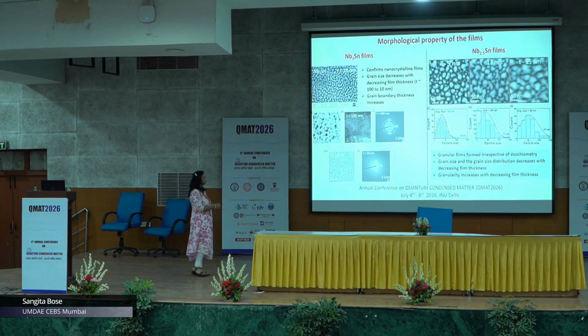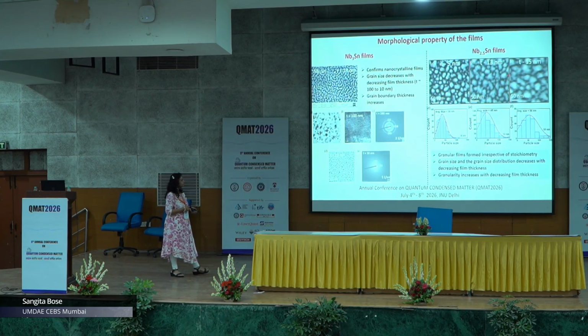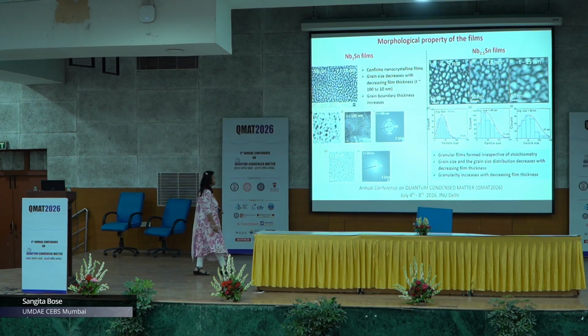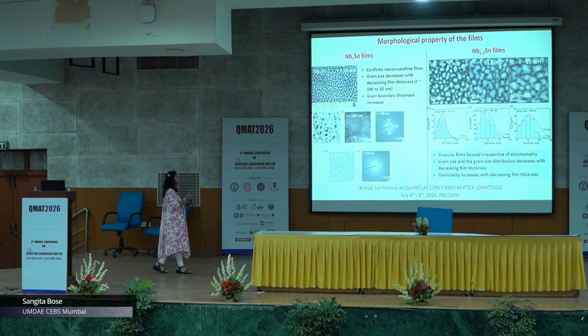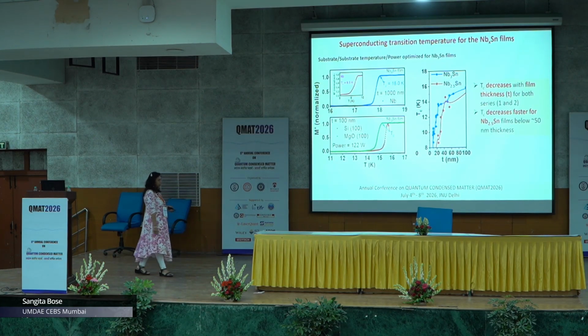Now, when we grow these niobium 2.5 tin films, this of course shows a similar microstructure as the niobium 3 tin films, but to really see the granular microstructure, we go to very low thicknesses of about 9 nanometer. What we notice is that when we reduce thickness by very small amounts, the average grain size is given here, you have small grain sizes, but you also get a grain size distribution, which is obviously known. So, granularity increases with decreasing film thickness, and this will have some bearing on what I will show you later on in our results. Okay. So, first when we grow the films, we have to of course characterize the superconducting properties.